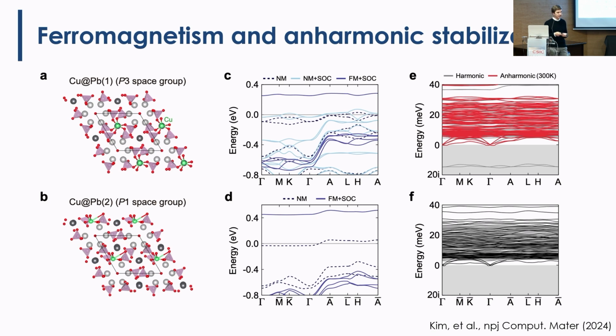So I was contacted by the group of Tomeu Montserrat in Cambridge. I don't know if you know him. He's an ab initio guy also doing models, and he contacted me because apparently the crystal structure of this LK99, a copper-doped lead apatite, is unstable in the standard calculation. What I mean by unstable dynamically is that it is not in a minimum of the Born-Oppenheimer energy surface.